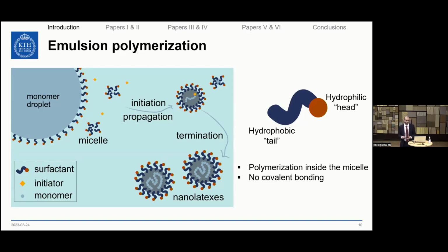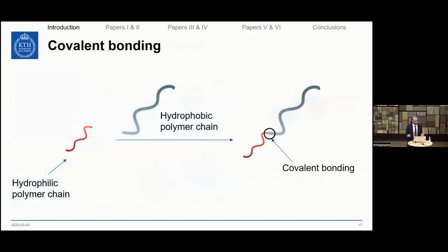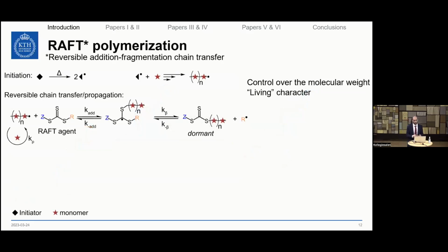and this can lead to some unfavorable effects. So we need to find a way in order to covalently link a hydrophilic polymer chain with a hydrophobic one. And in this thesis, we have used a controlled radical polymerization technique known as RAFT, which stands for reversible addition-fragmentation chain transfer polymerization. In this case, we have used a chain transfer agent, also known as RAFT agent, which controls the molecular weight of the final polymer.